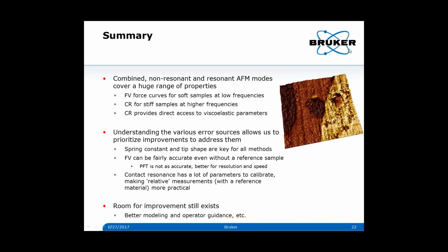Thank you. It says pre-calibrated probes with a predefined tip shape and radius is a good idea, but how long when using the probes in experiments will those values hold true? Would you recommend characterizing the radius and shape again yourselves after use? So it depends on what the sample is. These tips, because they're a little bit less sharp, are very robust on hard samples, and we don't typically see much variation. Now, what can happen is the tip can pick up some material, and if there is a thin layer of polymer on your tip, then your tip is not behaving as it was originally intended, and that's where you need to go back and do a tip clean or something like that to remove that.